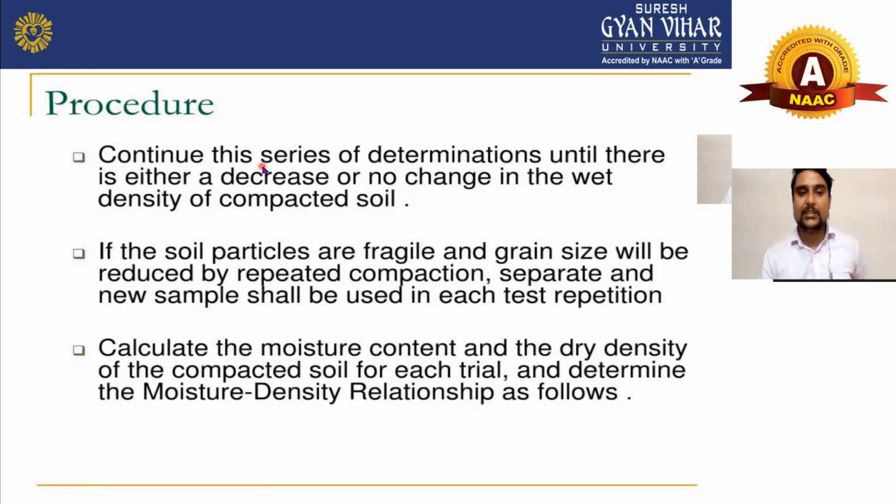Continue this series of determinations until there is either a decrease or no change in the wet density of the compacted soil. You have to do this until you get the optimum density of your soil, and it will change. It may increase or it may decrease. Keep in mind that when your density starts decreasing, you have to stop.